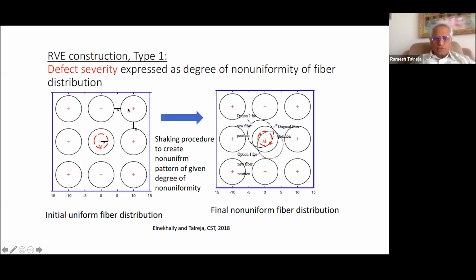So what we do is to look at the maximum distance a fiber can travel or move when you shake it. And if you allow it to move that maximum distance and create, through random generation of numbers, new positions, then the final product that you get here has the maximum non-uniformity. So we call it 100%. And then we reduce the size of the circle in which you can have the centroid of the fiber take different random positions, and proportionately then you say it's not 100%, but 50% or 30%.